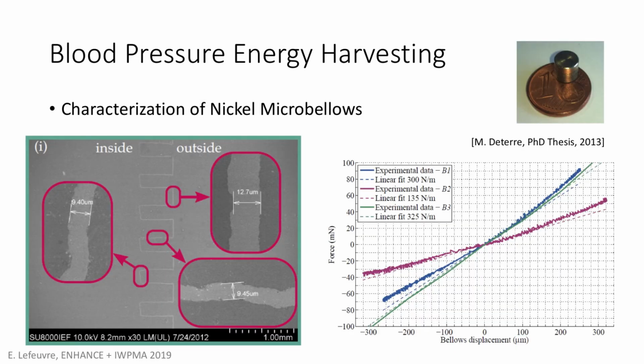Once it was fabricated, we first characterized several samples to check that the force versus displacement is compatible with our simulations and our needs. You have here several different slopes, because the process was not perfectly repeatable, but as you can see on the linear fit, the stiffness is between 135 and 300 Newton per meter, which is totally compatible with the application.